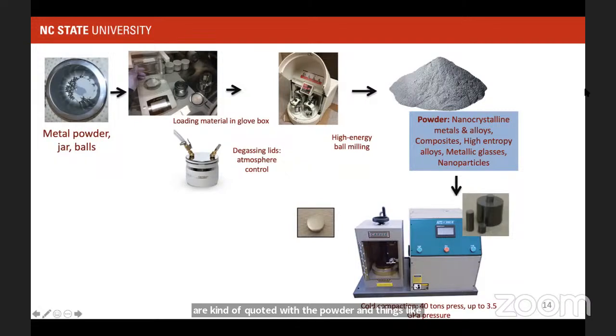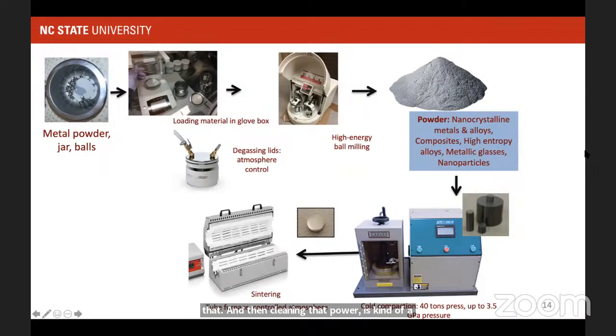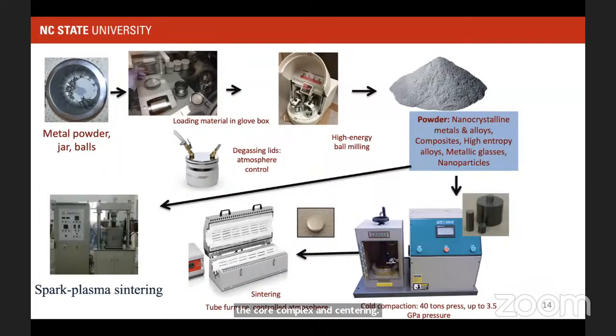Once the powder is made, we can use cold compaction, sintering, or spark plasma sintering. Depending on what we want to do, we have different methods to consolidate and make our samples. Our samples more or less look like that. We make small pellets and look at the properties. We can also use this powder for additive manufacturing, for cold spray, and a variety of other applications.